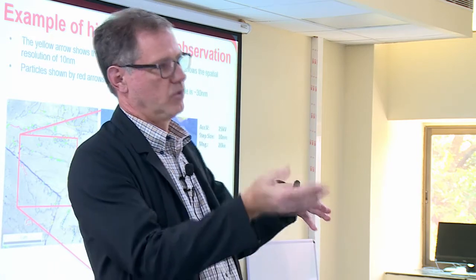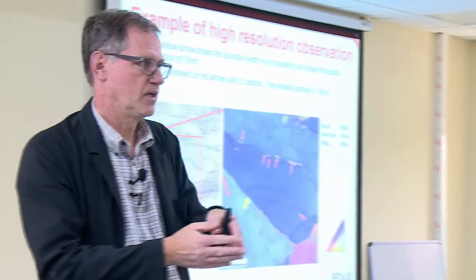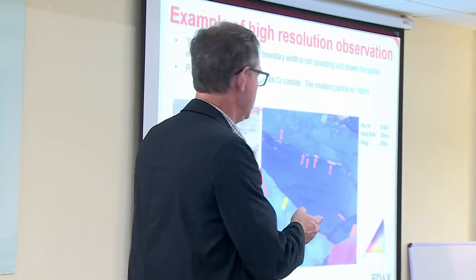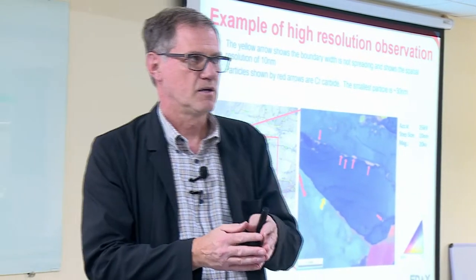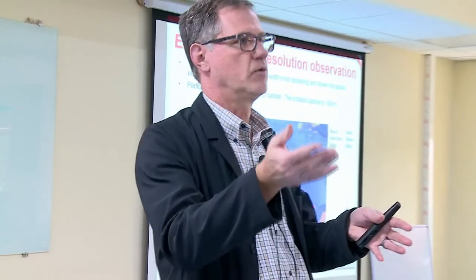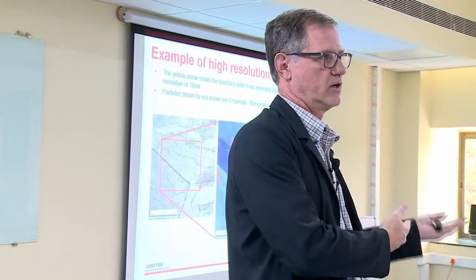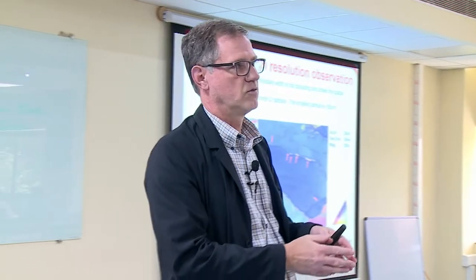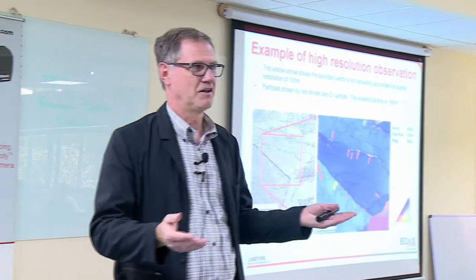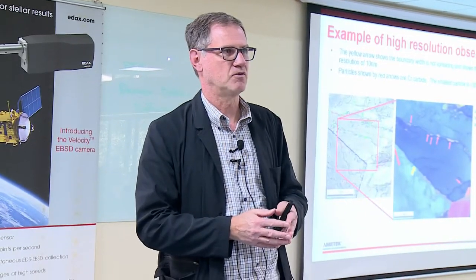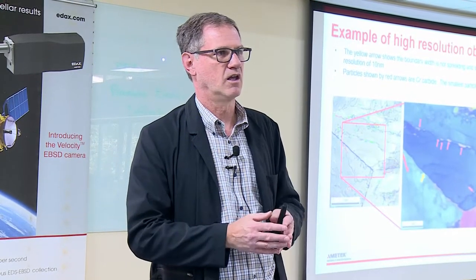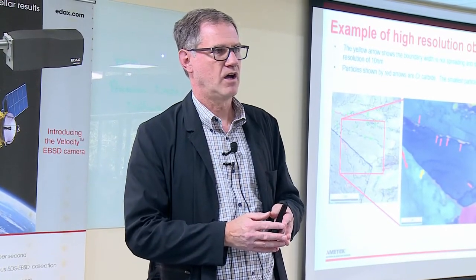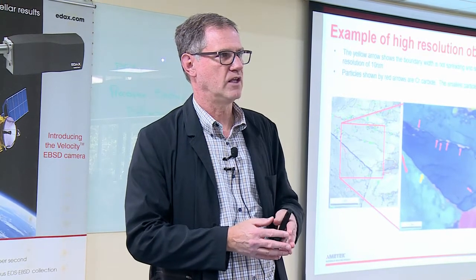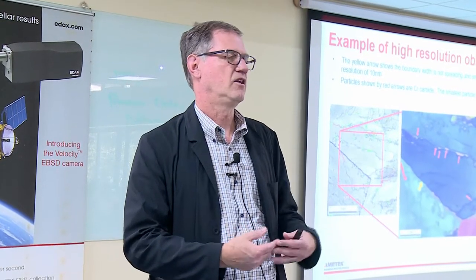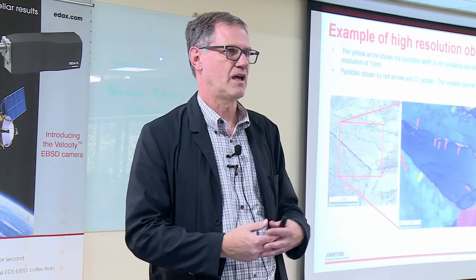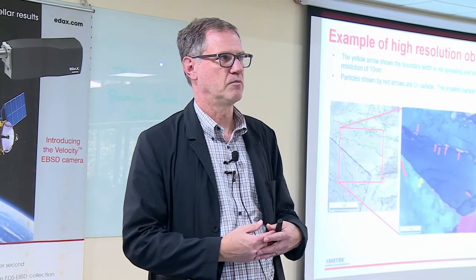Now, you bring up a really good point about the TEM, and that is because if you want to do EBSD and TEM together, sometimes as soon as you hit it with the electron beam, you've destroyed the sample and you can no longer use it. And so that's really difficult, and I don't have a lot of good answers except to work at lower voltages and lower currents. And so I guess if you're doing that, you'll have to do the least aggressive first, but that may not work. I know that can be a problem.